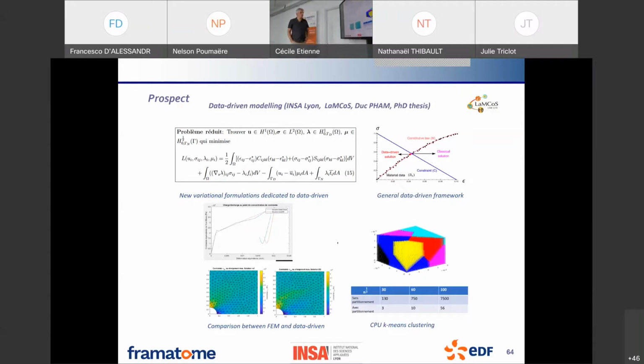So in order to develop the data-driven solutions, we can use such a Lagrangian, for instance, where the star quantities on epsilon and sigma correspond to possible experimental data. There is a key point, in fact, in data-driven modeling in order to build, for instance, virtual twins for welding or the kinds of multiphysics or multiscale problems. We assume that we have data. We assume that we have experimental data. Or in fact, in practice, it is not so easy in solid mechanics, for instance, to have experimental data.